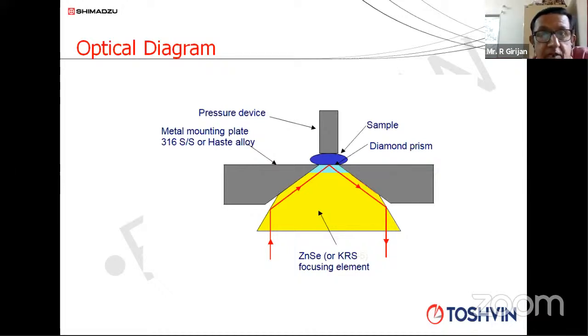Then in that case, what is the solution? Go for a diamond ATR. And everyone knows diamond is the hardest material. Here, the yellow color is the primary crystal. It can be KRS5 or zinc selenide. Over it you can see a slight blue color, that's a pure diamond we are keeping. You keep the sample on the diamond and apply pressure to make the sample flat. Because diamond is so hard, nothing happens to it. And the light beam will come. It is called a single reflectance diamond ATR, a single bounce ATR, because there is only one bounce. You can see the light path coming from the source, going to the material, and going back to the detector.